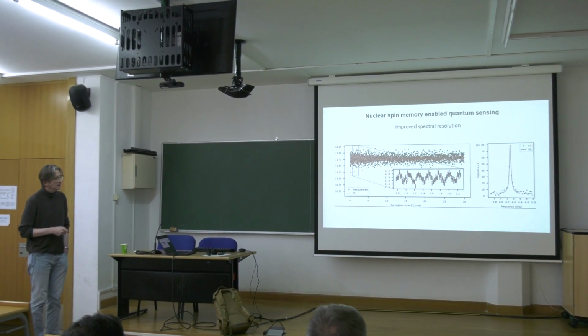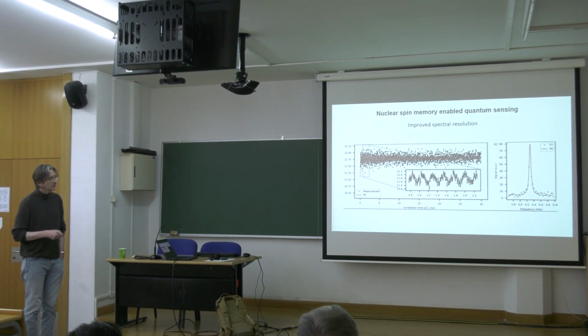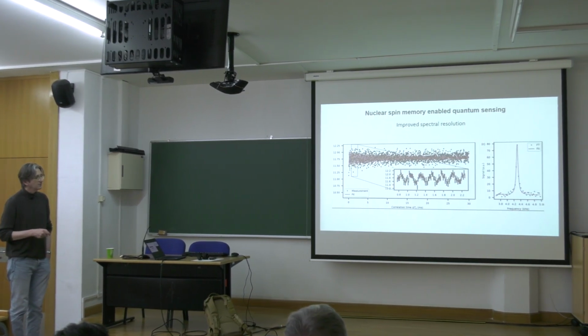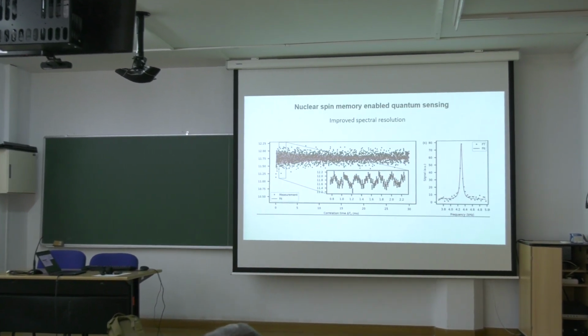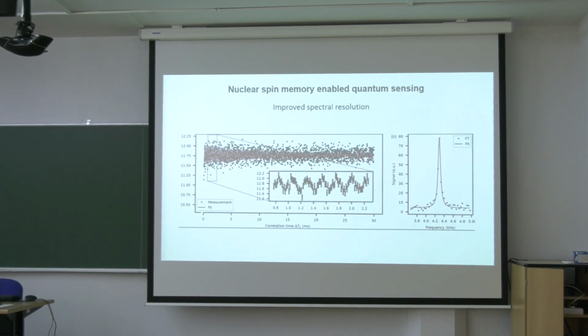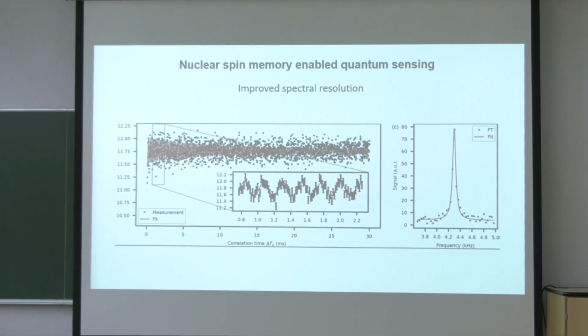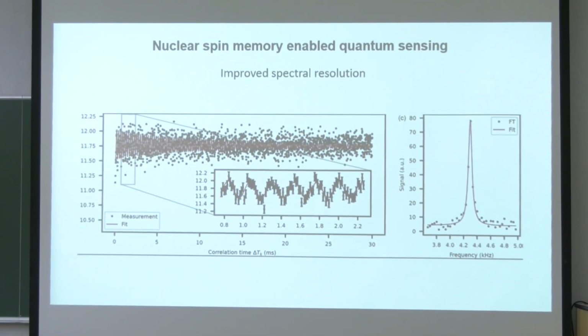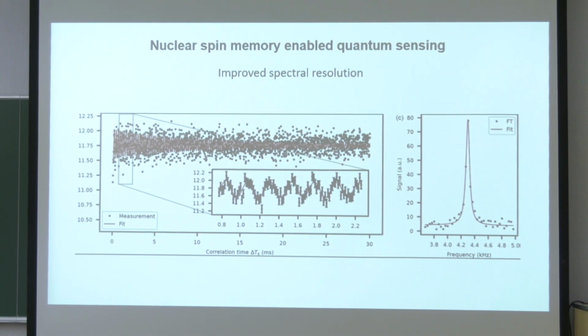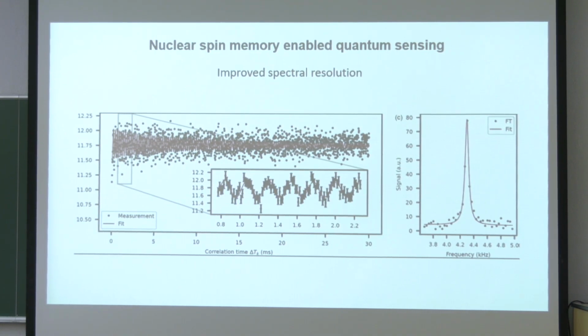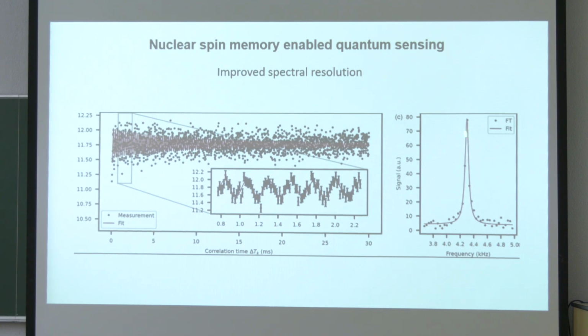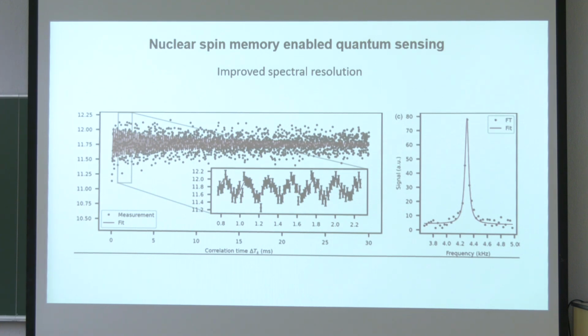And so here you see the trace showing the oscillations of the NV center as a response to the external signal, and the time scale here is about 30 milliseconds, so it's much longer than the decay time of the electron spin of the NV center by phonons, and it's now limited by the T2 time of the nuclear spin. So if you do a Fourier transform of this waveform, you get a spectral line of the external signal which has a line width of a few tens of hertz, so beyond the T2 time of the electron spin.